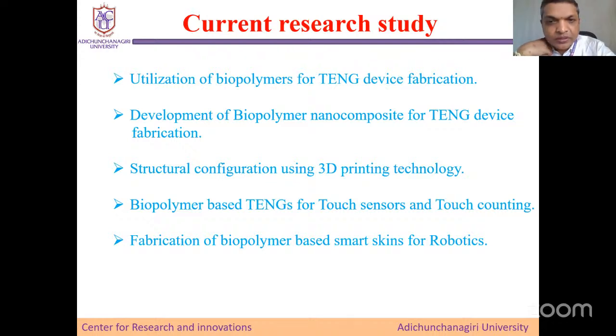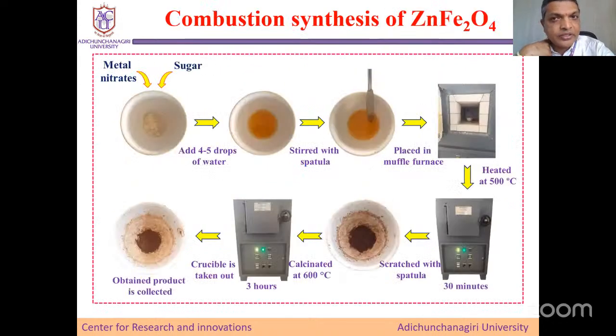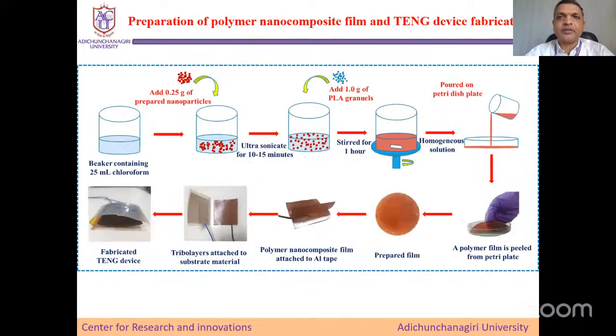See here, this is the combustion synthesis of ZnFe2O4, which is a semiconducting material. This is the procedure: adding metal nitrates and sugar, stirring with a spatula, and placing in a muffle furnace. It is a simple combustion process to synthesize nanoparticles. At the end, you get ZnFe2O4 after calcination, and the crucible is taken out, and this nanoparticle is subjected to other characterization.